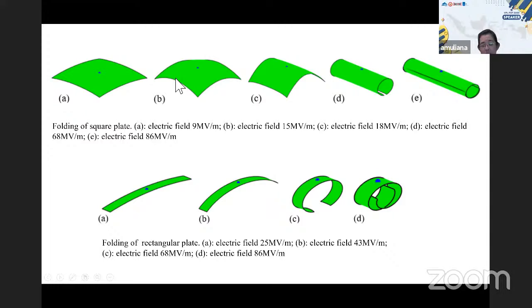The reason it cannot sustain the dome shape is because we start with a flat panel, right? The Gaussian curvature of this flat panel is 0. So when we just apply an electric field, we tend to create a shape, but we cannot create a dome shape without stretching. The only shape that can be created without stretching or cutting the sample is one with zero Gaussian curvature, right? Because it starts with a flat panel with zero Gaussian curvature, it ends up in this rolling state. The same thing happens with a stripe, and it's easier because of the aspect ratio.